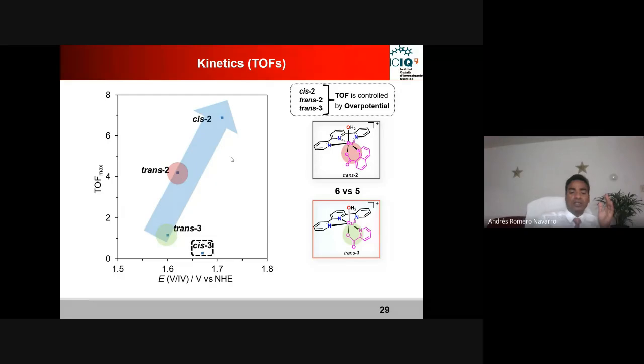And then we found that this potential is basically, let's say, at the high valent ruthenium 4,5 redox couple. So higher is this, and this also can give you the idea of the overpotential. So higher is the overpotential, better is the activity. And that is what the Marcus theory supports, and that is what we got exactly in the system.